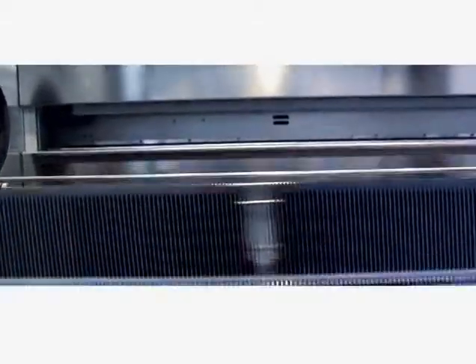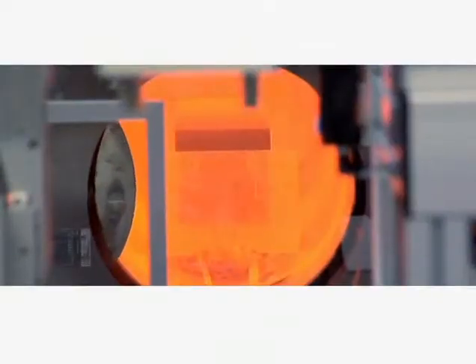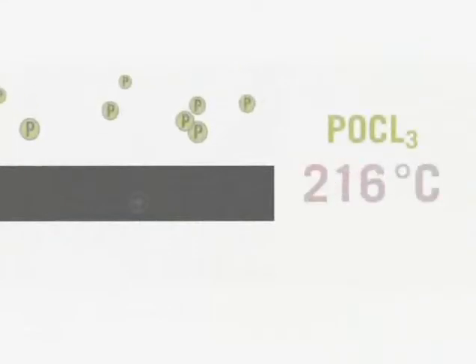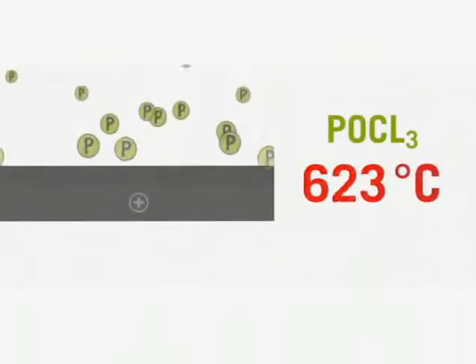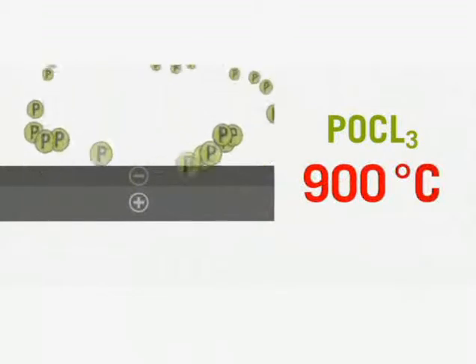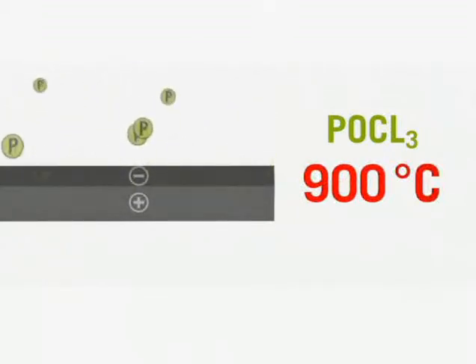Because the plastic magazines would melt in the oven, the raw wafers are transferred onto process boats made from quartz. The wafers are exposed to a phosphorus-based atmosphere in the oven. The high oven temperatures cause the phosphorus particles to diffuse into the wafer. This in turn causes the wafer surface to convert from a positive to a negative conduction type.